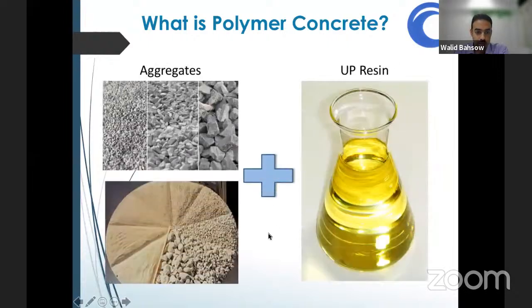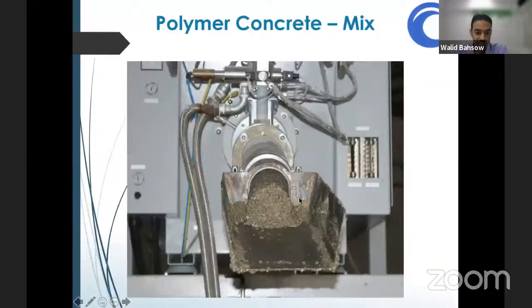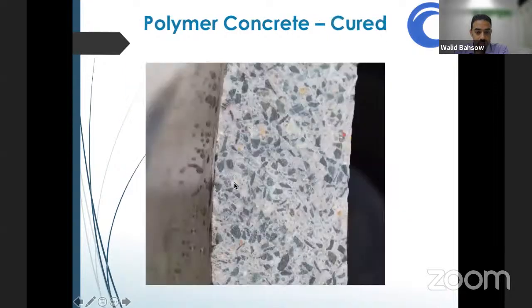Again, the contents: basically you have a mixture of the aggregates, stones and sand, mixed together with the unsaturated polyester resins. This is what the mixture looks like, just as it comes off the machine. Normally, the ideal way is to use computer-controlled machines to ensure that the batch mix is consistent and the quality is constant from mix to mix. After it is cured, it looks like this.